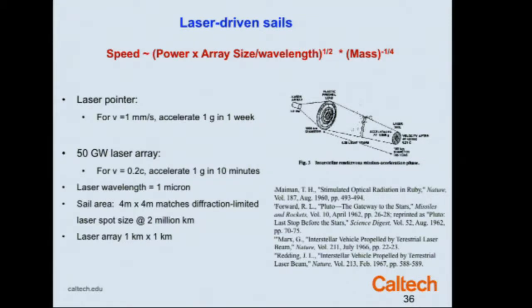So I'm going to have more laser power than that. That's why I need a very high power, maybe 50 to 100 gigawatts to get to 0.2 C to accelerate 1 gram in 10 minutes using a laser with a wavelength of 1 micron, a sail area of 4 meters by 4 meters that produces a diffraction limited beam spot size at a size of 2 million kilometers.